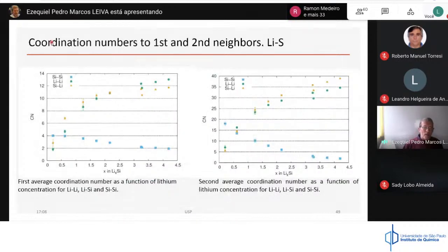Another thing that you can investigate is the coordination number to first and second neighbors. You can get, for instance, the coordination number of lithium with respect to lithium, which is this line. As a function of the quantity of lithiation, you can see that if you put more and more lithium atoms in the system, your number of nearest neighbors goes from, let's say, 2 to practically 12, which is very close to a close packing structure. The novelty here is when you look into silicon.